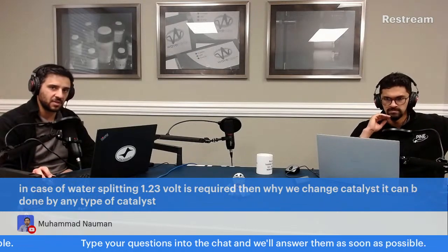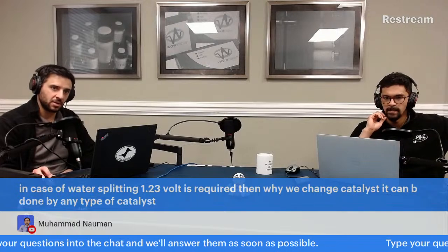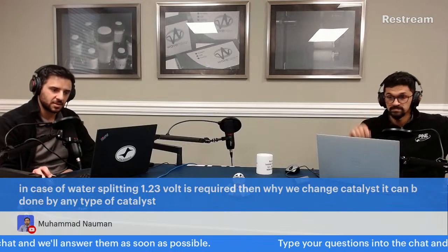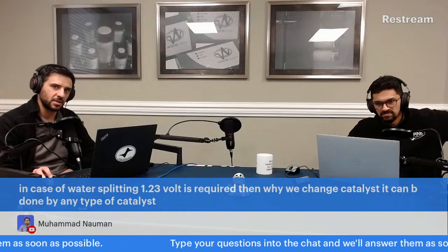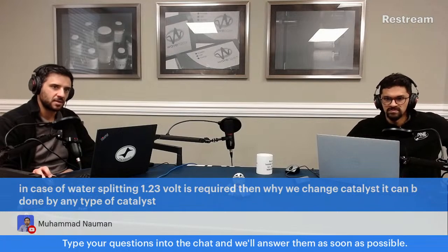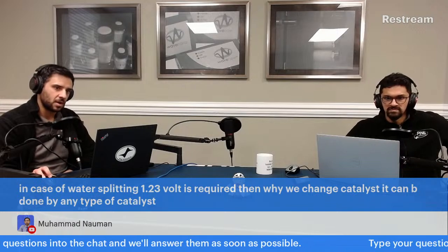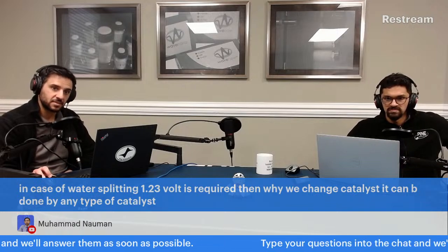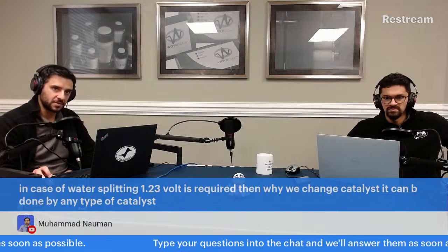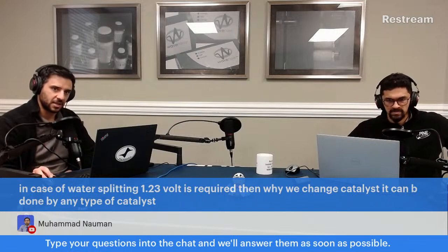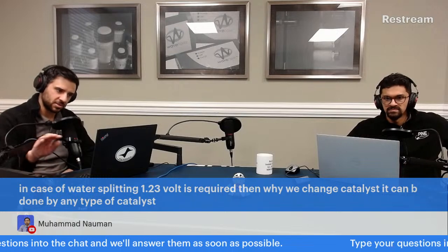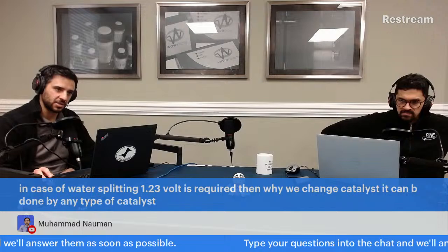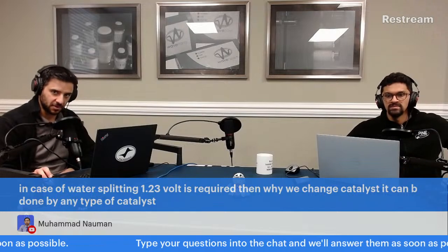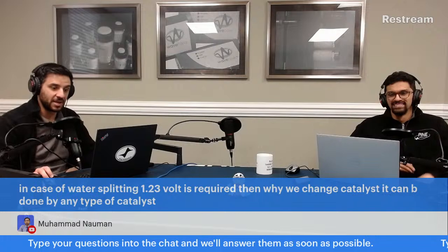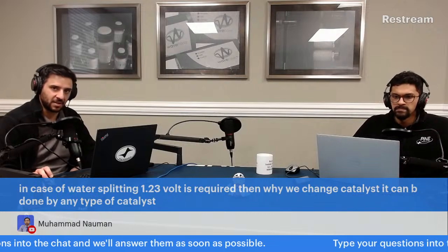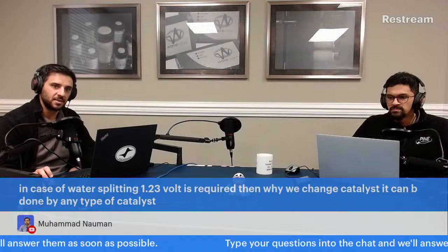It's just like I said, if you have glassy carbon and you saturate your solution with oxygen, try this, it'll be a fun experiment for you. Get a glassy carbon electrode, get sulfuric acid, and saturate it with oxygen gas, and then start at 1 volt versus RHE and start scanning negatively and watch for when it actually starts dipping negatively and reducing oxygen. It takes a lot of volts. It doesn't happen right away. Glassy carbon's a terrible ORR catalyst, which is good.